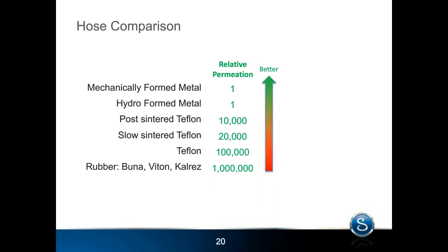And if you look at relative permeation rate, if you say metal is a 1, so very, very low permeation rate, a post-sintered Teflon permeates about 10,000 times more than that. A slow-sintered Teflon about 20,000 times more. So a slow-sintered permeates about twice as much as a post-sintered. Normal Teflon, though, permeates about 10 times a post-sintered Teflon. So that post-sintering process cuts the permeation rate of a Teflon to 1/10. And so that's the advantage there. And that slow sinter process, you can see, cuts it to 1/5. And then rubber hoses will permeate the fastest because the material structure has the largest holes between the molecules of the hose.